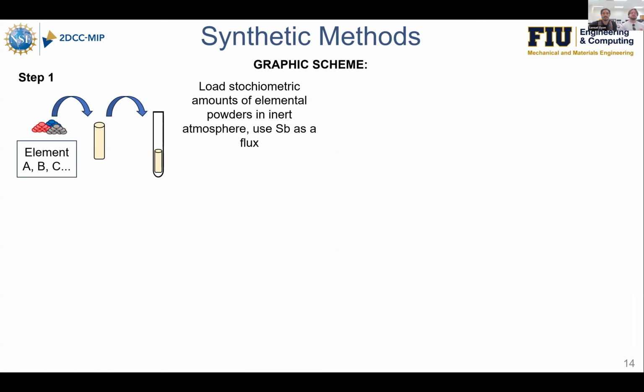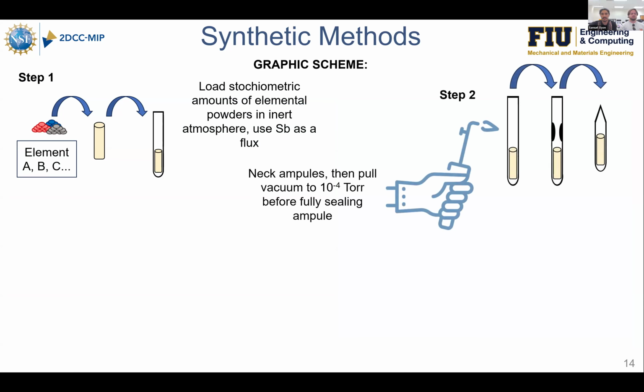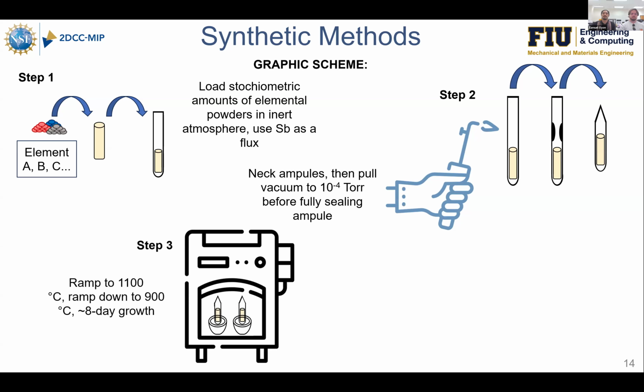first we loaded these elements in stoichiometric amounts in an inert atmosphere in a glove box, and that was then loaded onto a crucible. We used antimony as a flux, and that was then loaded onto an ampule. This ampule is then taken out of the glove box and taken for necking and sealing. During the sealing process, it reaches vacuums of up to 10 to the -4 torr, and once it is fully sealed, we are then able to place it in a furnace.